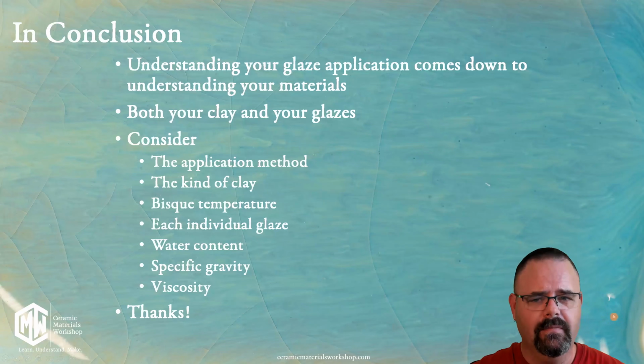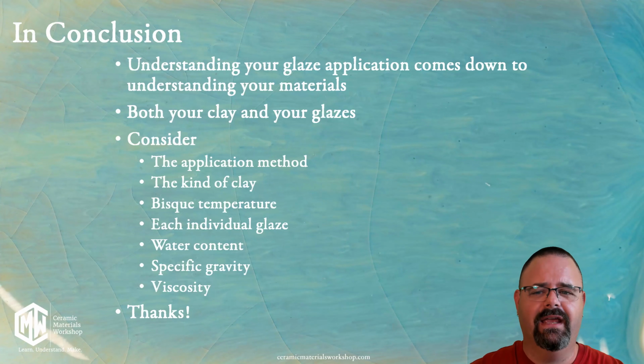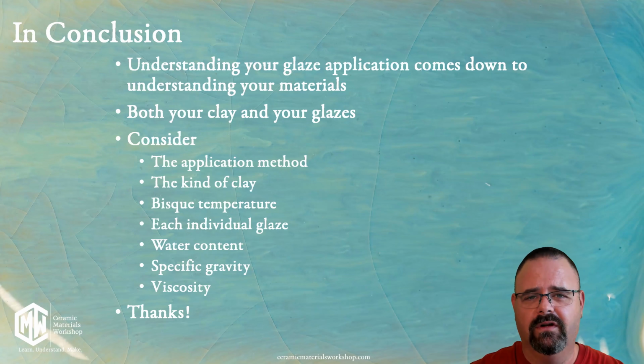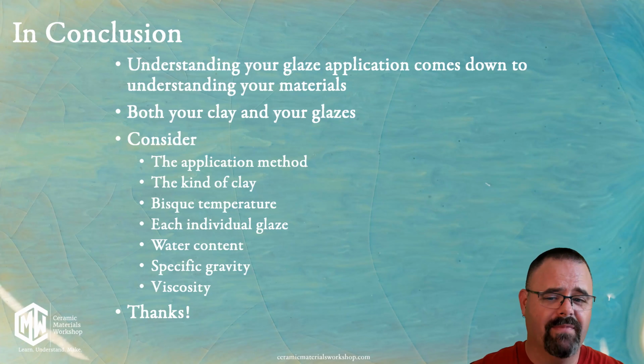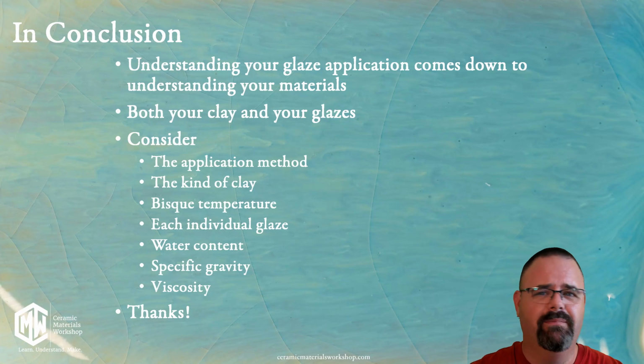So, understanding your glaze application really does come down to understanding your material, both your clay and your glaze. And we really want to emphasize going forward that you should consider everything that goes into your glaze to get a consistent application. The method of the application, whether it's dip, spray, or brush, or something else, the kind of clay that you're using, the bisque temperature that you work at, the fact that each and every glaze is going to be different, the measured water content, the specific gravity, and the viscosity all come together to help you understand your glaze and make it better.